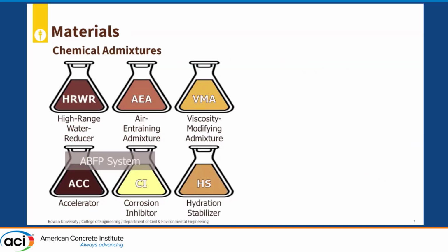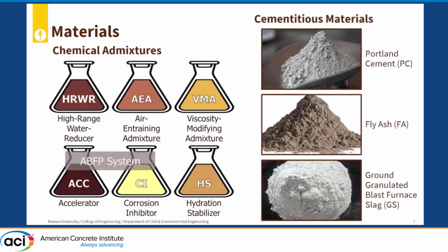To develop our SCC mixtures, we use several admixtures. We have high-range water reducer to improve workability, air entraining admixture to modify air content, viscosity-modifying admixture on some of our mixes as viscosity modifier, our ABFP system comprising of accelerator and corrosion inhibitor, and we also investigated using hydration stabilizer to see its effect on the fresh properties of SCC under freezing temperature. Since SCC uses a lot of cementitious material, we also explored adding supplementary cementitious materials, or SCMs. Whenever SCMs are present, they amount to 25% of the total weight of the binder.